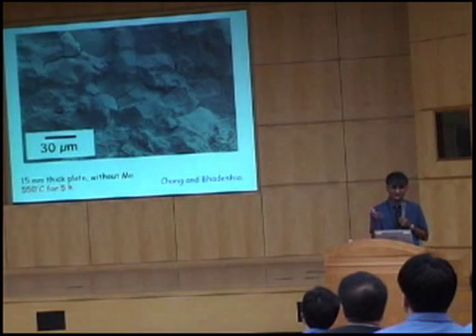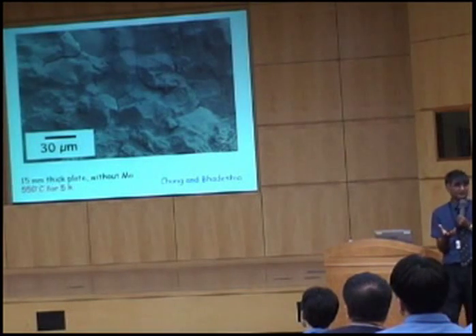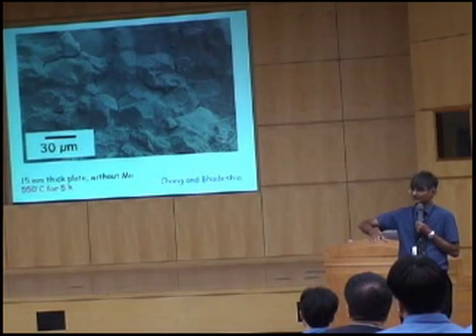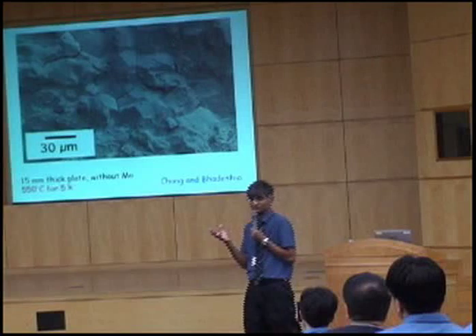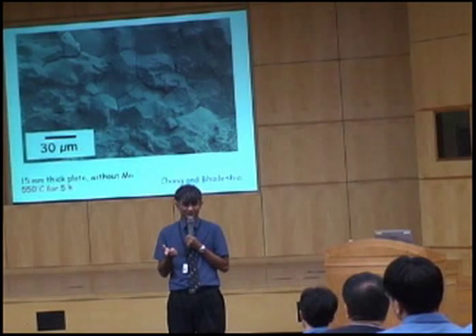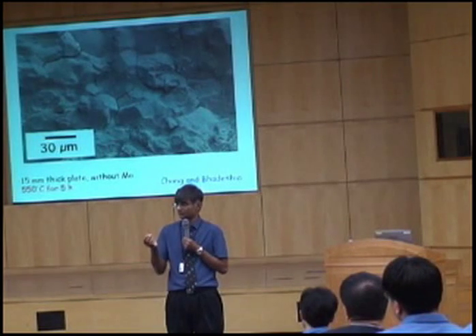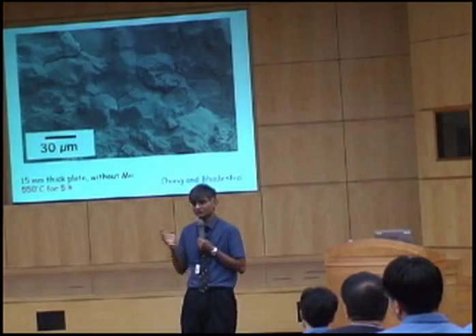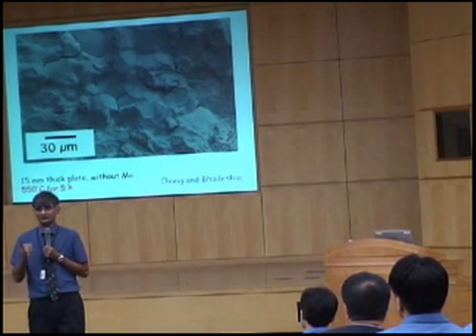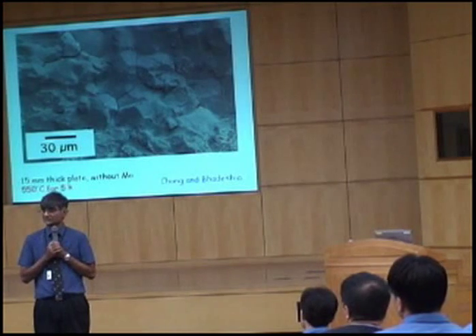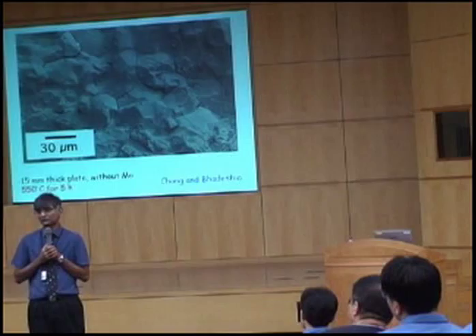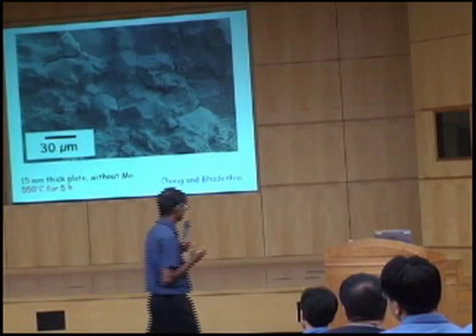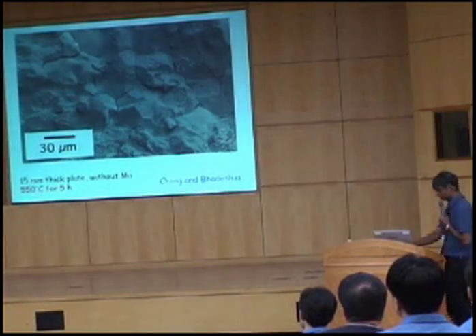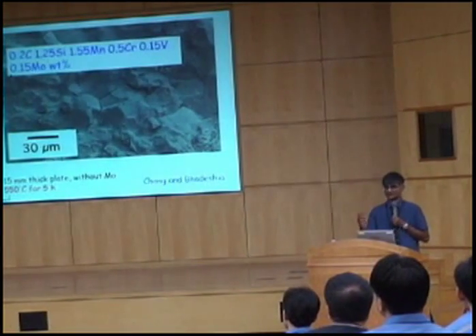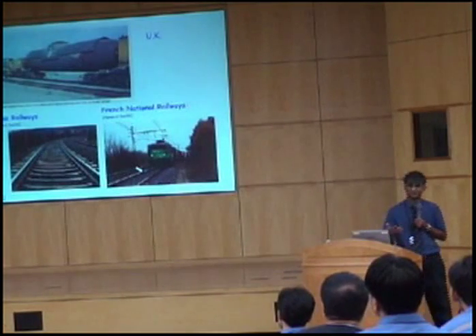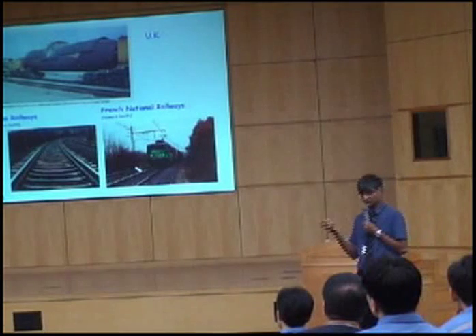So what happened was, with the larger rails, we had intergranular failure because a larger rail cools slowly. And you cannot say to the steelmaker that, look, you have to reduce the phosphorus concentration to zero. That's not possible in practice. So what do you do? Supposing you add a quarter weight percent of molybdenum, and again, this is very well-known, well-established in the literature, then it will stop the phosphorus from having an embrittling effect by stopping it from diffusing to the austenite grain boundaries. So all you have to do is add a quarter weight percent of molybdenum to the alloy, or less than a quarter in this case, and the problem disappears. You can get rid of the problem of phosphorus embrittlement.